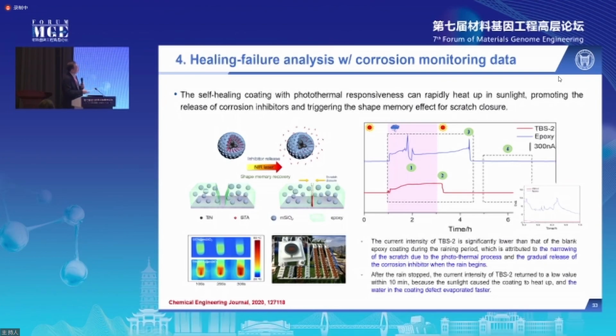This is because after the sun came out, it generates heat and quickly evaporates the solution stored in the coating scratch. But for the conventional coating, there's no heating, no scratch closure, and this is a wide open scratch. It takes longer for water to evaporate, so that's why it takes longer for corrosion to be suppressed. So this is already showing that with this kind of very high throughput and very frequent data acquisition, we can understand how self-healing actions occur in a real environment.